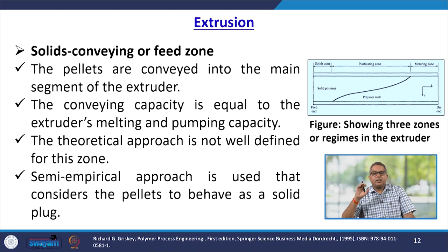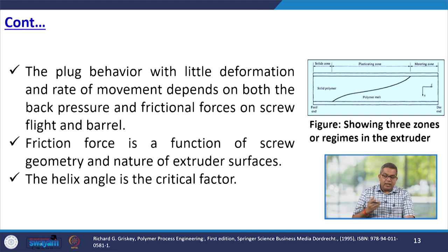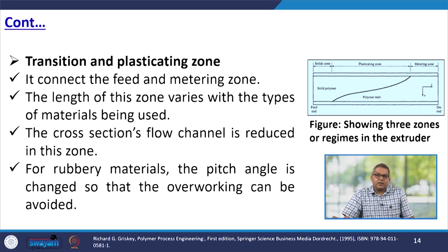Now, a semi-empirical approach is used that considers the pellet to behave as a solid plug. Now, the plug behavior, with little deformation, and the rate of movement depend on both the back pressure and the frictional forces on screw flight and barrel. Frictional forces also play a crucial role, as they add heat. So, the frictional force is a function of screw geometry and the nature of the extruder surface. A rough surface may create more frictional force and thereby impart more and more heat. The helix angle is the critical factor.